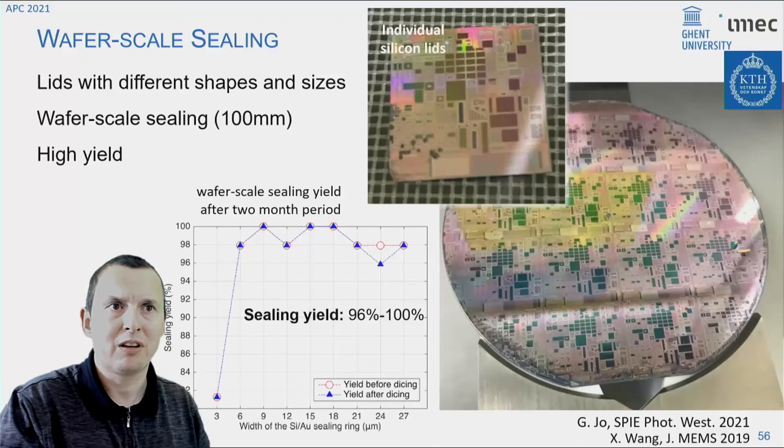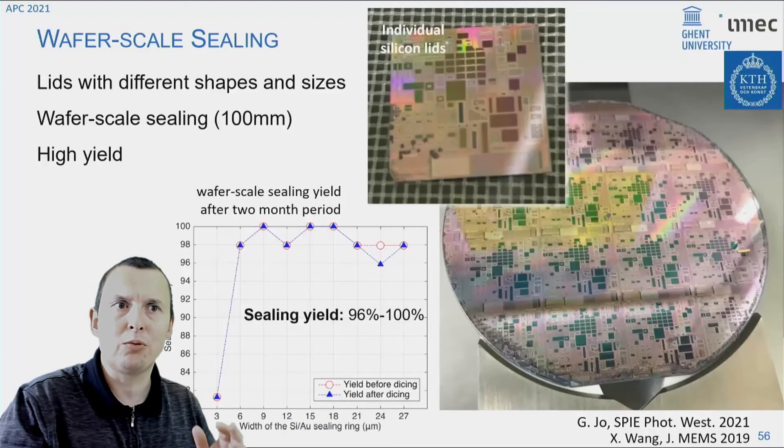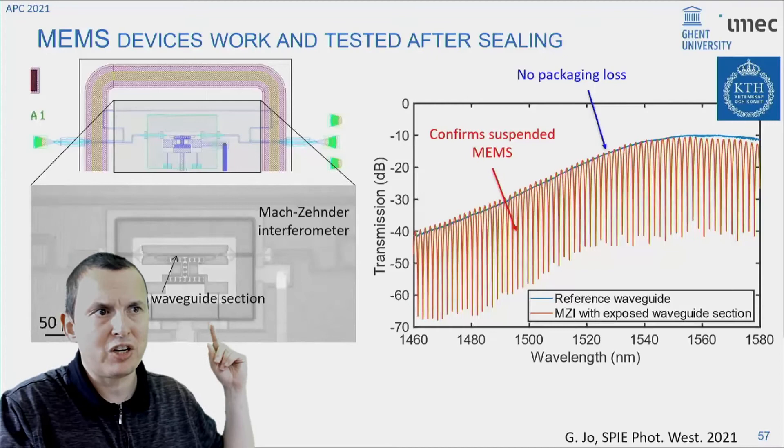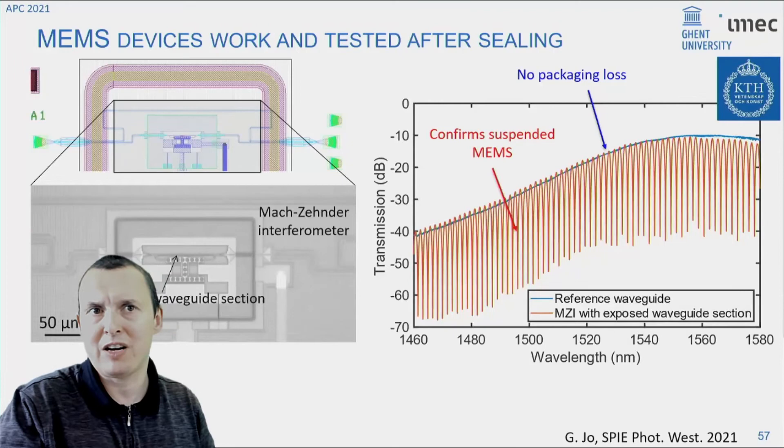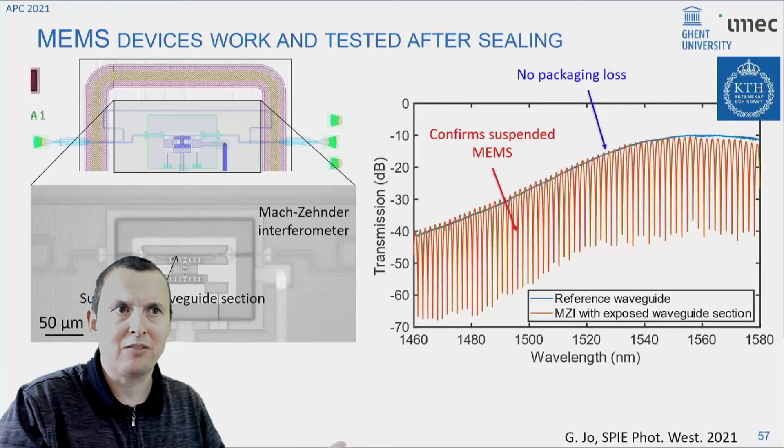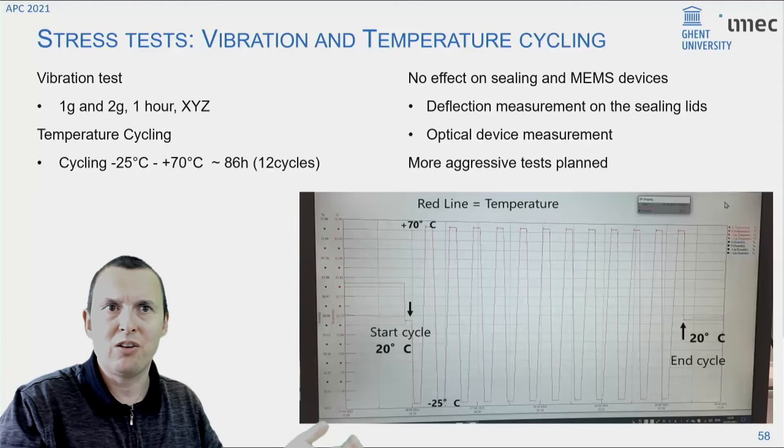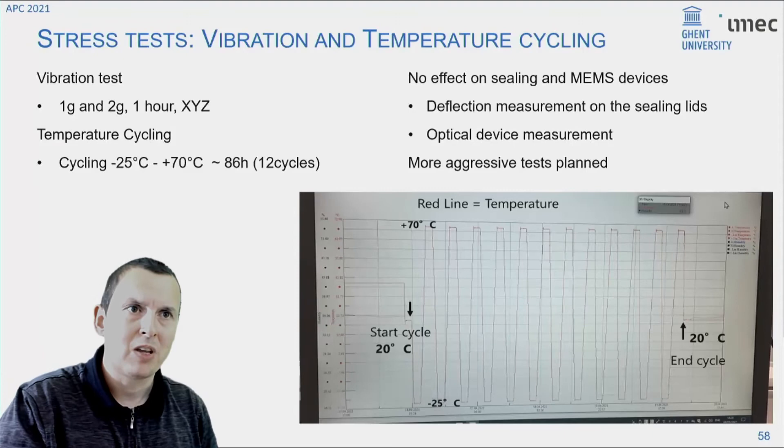The second problem, if you expose these devices to air, is that they are liable to damage. So they're exposed. If a dust particle falls on one of these MEMS devices, it's broken. So for long-term reliability, you need to cover them up. And so what we've come up with in the Morphic project is a local sealing mechanism where we apply a silicon lid on top of one or more MEMS cavities by thermocompression bonding. So we use the metal features that are already present in the platform to create these sealing rings, which can then be used to apply a silicon cap that is sitting on top of the MEMS device. And this can be done in vacuum or in a controlled gas environment. And the process is wafer scale.